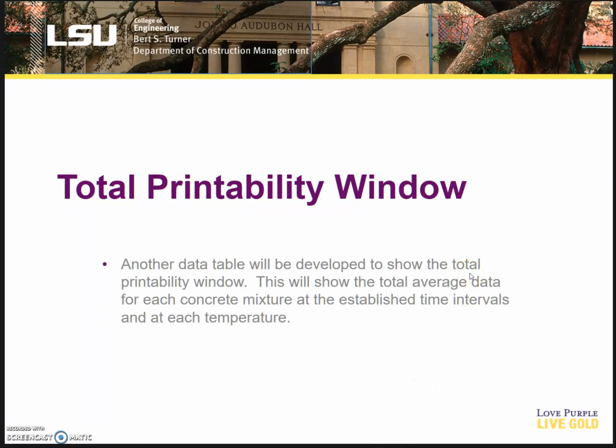So from here, we'll have both our initial set and our print limit. So we will then be able to show our total printability window, which will be the total time at each temperature for each cement mixture. This will show the total average data for each concrete mixture at the established time intervals and for each temperature. And we can see the total print window and conclude whether or not cold weather has indeed lengthened the print window.